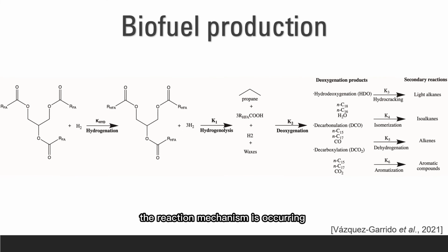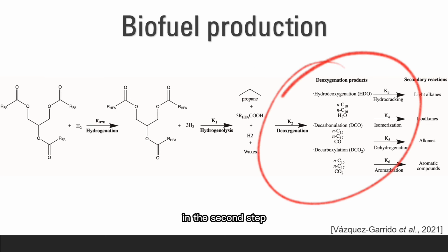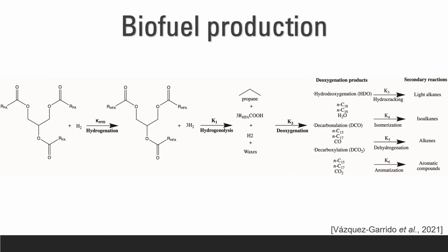The reaction mechanism occurred during the catalytic hydroconversion of triglycerides. The first step is the hydrogenation of the carbon-carbon bonds of triglycerides followed by a carbon-oxygen hydrogenolysis reaction, leading to the formation of 3 moles of free fatty acids and 1 mole of propane. In the second step, oxygen atoms from fatty acid molecules are removed in order to form light chain hydrocarbons through a deoxygenation reaction. Free fatty acid deoxygenation can occur through 3 main mechanisms: hydrodeoxygenation, decarboxylation, and decarbonylation.